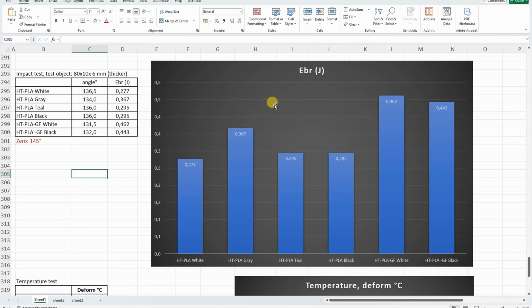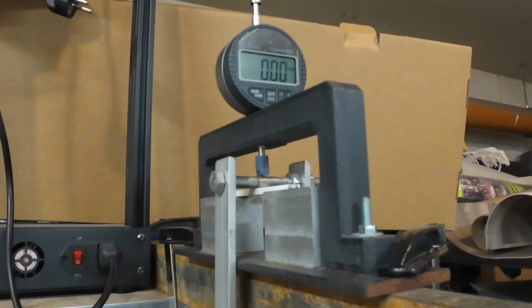The colors have more or less similar toughness, except one peak in the gray color, and I know as a researcher that I should reprint and check this, but I don't have time for this because I am late with the video. But what is quite obvious is that the glass fiber is tougher compared to the non-reinforced versions, which is not really a common case. 3-point bending test.